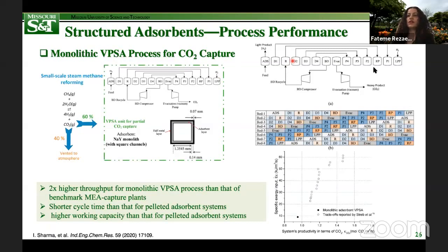As you can see here, the main finding of this study was that the productivity of the monolithic VPSA process in terms of its CO2 production capacity was almost double the values reported in the literature for benchmark amine scrubbing capture plants for larger scale steam methane reforming applications. It was also reported that the cycle time is much shorter than that for pelleted adsorbent systems under the same conditions with an equally sized fixed bed. The pelleted adsorbent system was also found to have a lower working capacity between the same blow-down and evacuation pressure than the monolithic adsorbent systems.